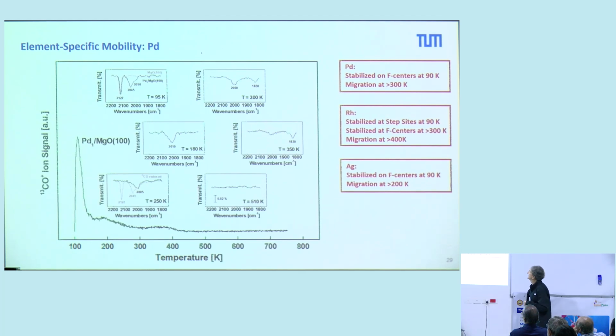And for rhodium, we observed that they are stabilized also at step sites of this magnesium oxide. But then at 300 K, they go to F centers, oxygen vacancies. And then at 400 K, they are migrating. Silver, they are not stable. Already at 200 K, they form larger clusters.